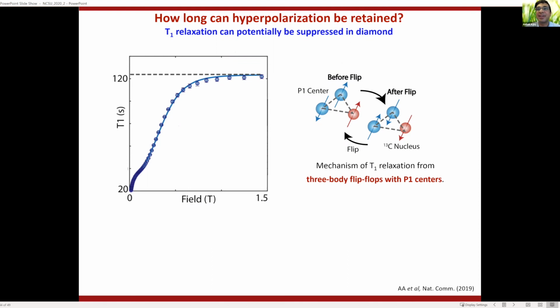I think there are many paths it can go. But this is very interesting, and this is one of the things we're trying to study, basically by producing a non-equilibrium spin state. So we're producing spin texture, like an onion shell of polarization, and we're trying to see how this spin texture diffuses in the lattice. But if you can stop it, then that means it's probably not spin diffusion, because if it were spin diffusion, it would just continue growing. If you can almost instantaneously stop it by operating optically the NV centers, then it's probably the long distance, 10 nanometers, maybe longer, coherent flips.